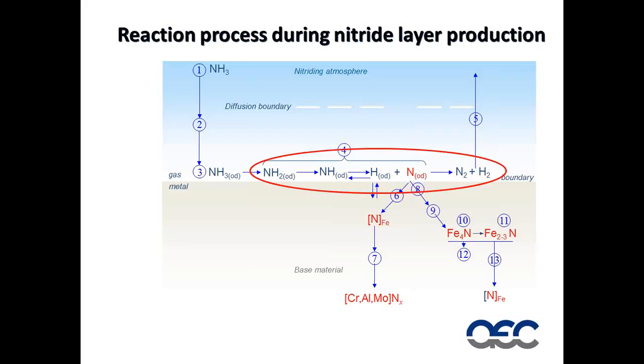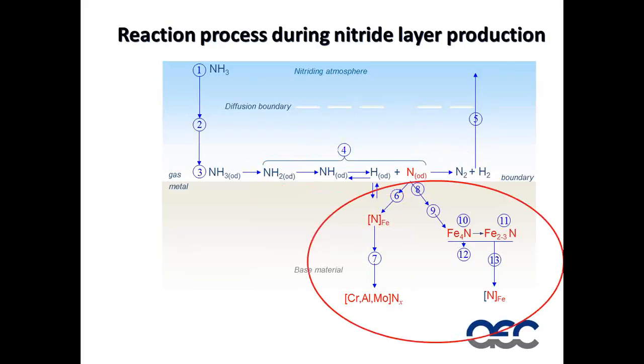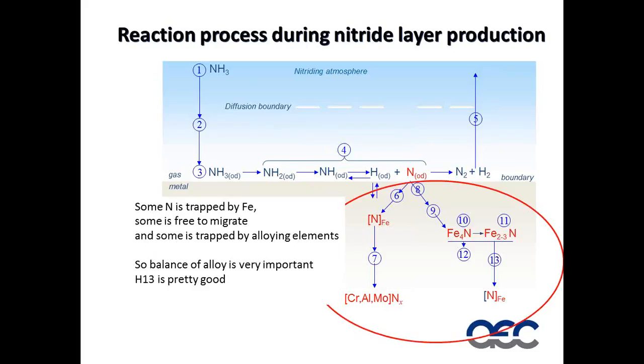Some of this recombines back into molecular nitrogen and hydrogen and simply returns to the nitriding atmosphere. This is a little bit of a waste because we don't get anything out of it. But some of the atomic nitrogen and hydrogen diffuses into the surface of the steel. The hydrogen, it's really not that significant in this process. Most of it combines to make H2, and at some point diffuses back out of the steel and we lose it. So it's not something we should really concern ourselves with. However, the nitrogen goes on to react with the steel. Some of the nitrogen is trapped by the iron, and that's this reaction we see over here to the right. We react iron and nitrogen together to make an iron nitride.